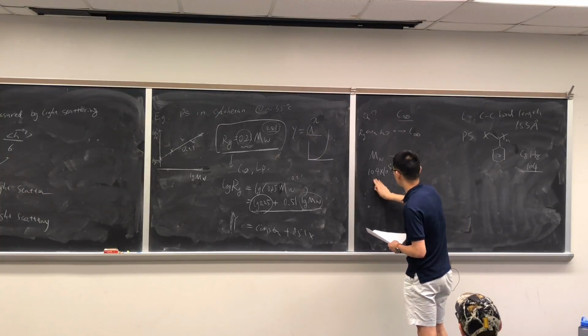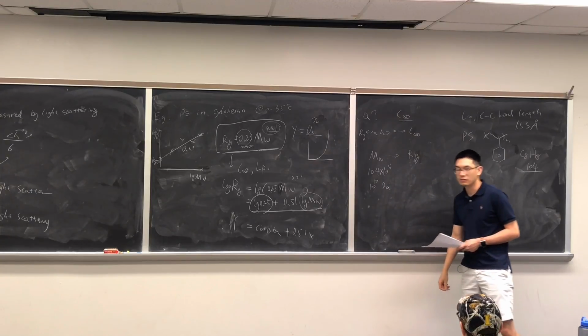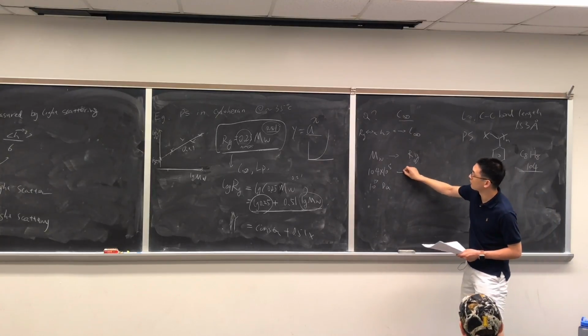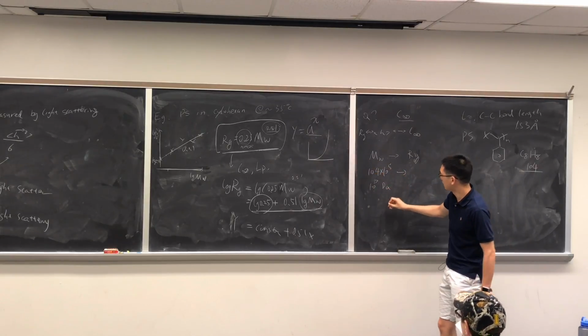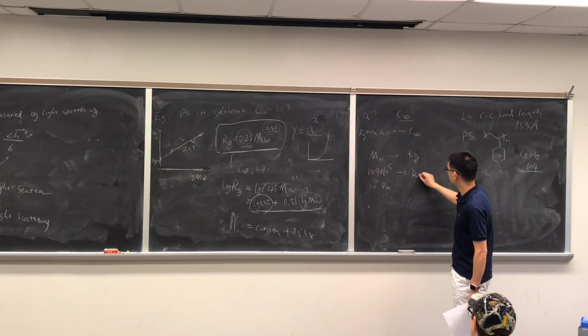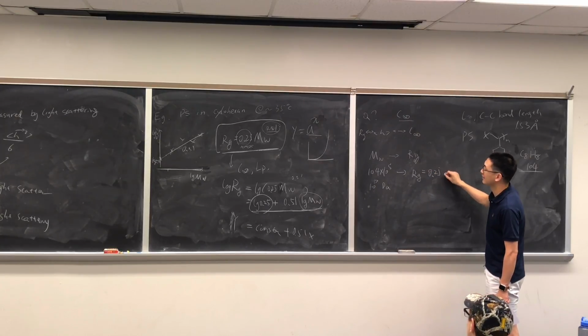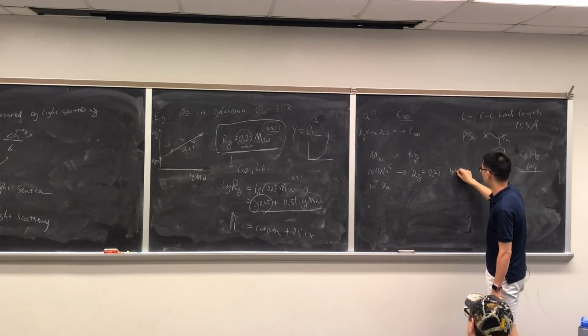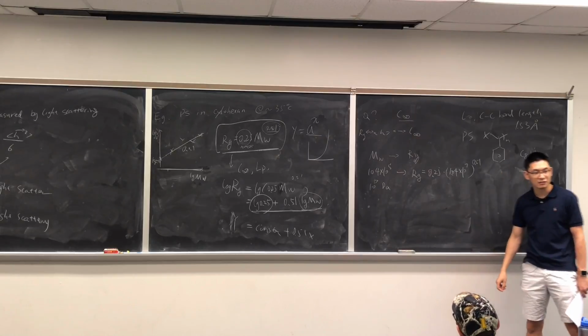Well, this is roughly 10 to the 7 Dalton, or grams per mole, right? Then you can calculate what this Rg is using the equation right there. Rg will be 0.25 multiplied by 1.04 times 10 to the 7th, to the power of 0.51, correct?